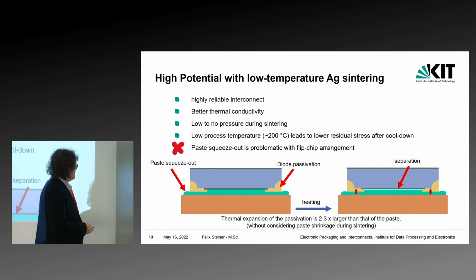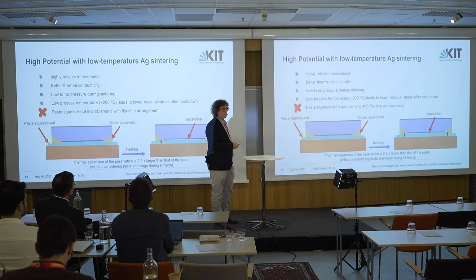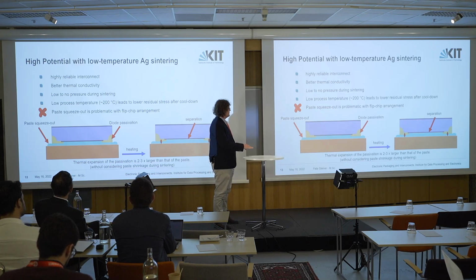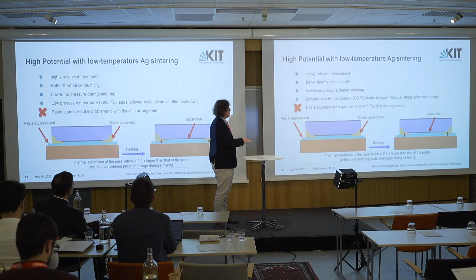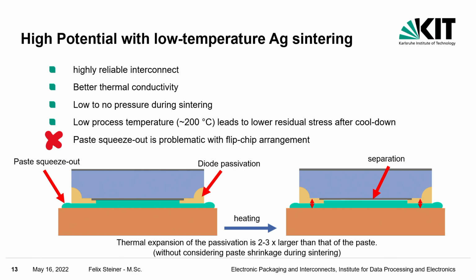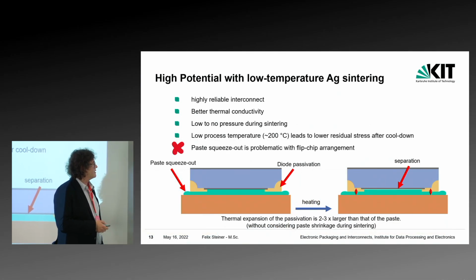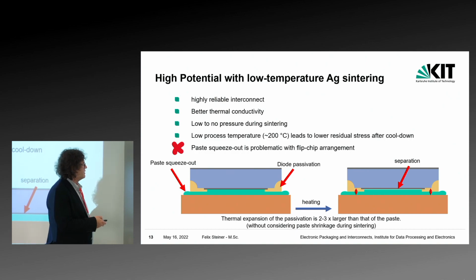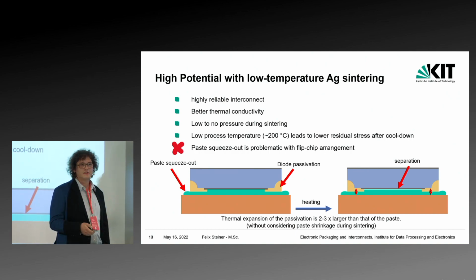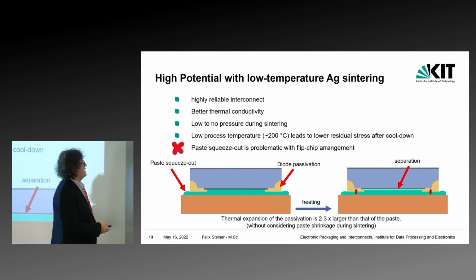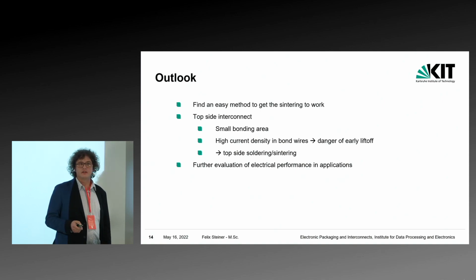But what you get is a paste squeeze out, because with pressureless pastes you work with wet pastes, where you press the die in, you get squeeze out, and then when you heat this up, the passivation starts expanding more than the paste, the paste CTE being around 20 to 30, and the passivation being at 40 to 60 or so ppm. So then you get this separation as on the right, where the diode gets separated from the sinter paste. So yeah, it doesn't really work until now, and until someone fixes this problem. So yeah, that's basically it.